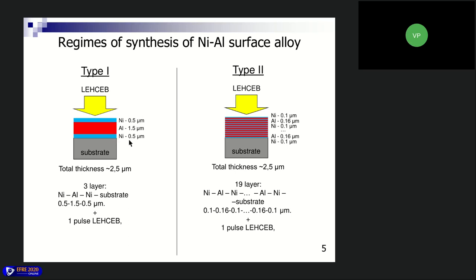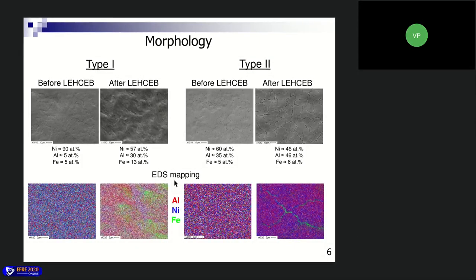Only three layers. The type 2 sample consists of more layers, 19 layers, which are thinner than type 1, but with the same total thickness of 2.5 micrometers. So we tried to investigate the difference in the forming of a surface alloy with thin or thick layers. On this slide, you can see the morphology of the samples of type 1 at the left part of the screen and type 2 at the right part of the screen.